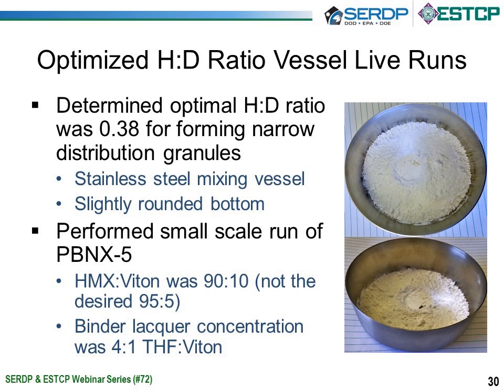So the optimized H-to-D ratio vessel that was determined in these inert runs was 0.38. We made a few of these stainless steel mixing vessels, and they were made out of stainless steel because we needed to ground the mixing vessels in order to avoid any ESD generation during the mixing activity. They also had a slightly rounded bottom in order to avoid any impingement of materials in a 90-degree curve at the bottom of the mixing vessel. So the rounded bottom actually gives you a little bit better mixing capability.